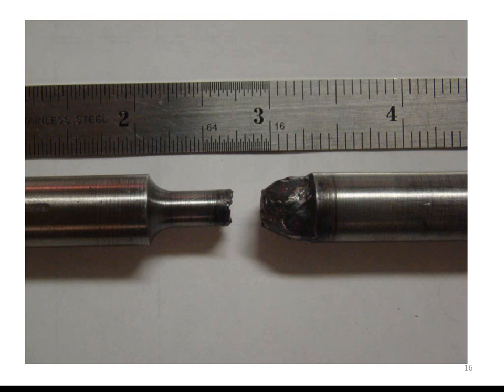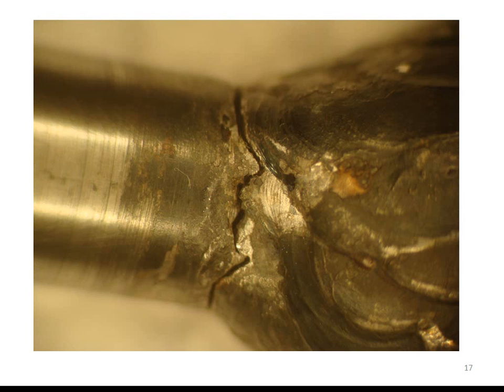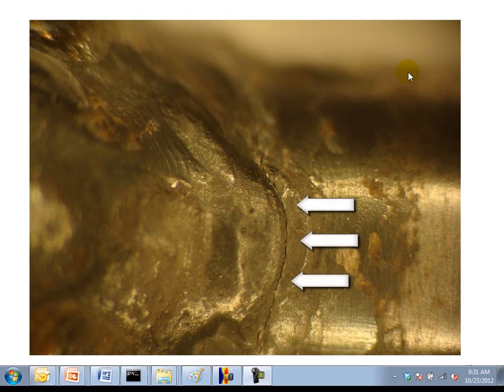This is a picture of a failure in a welded test rotating bar specimen. Here's a close-up of that weld failure. Here's an additional close-up of the small crack at the weld following the surface undulation in the material, as might be expected. Small specimen rotating cycle tests for carbon steel materials in the high cycle range can take us to